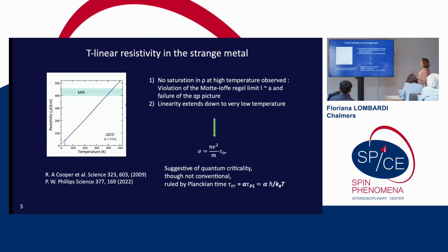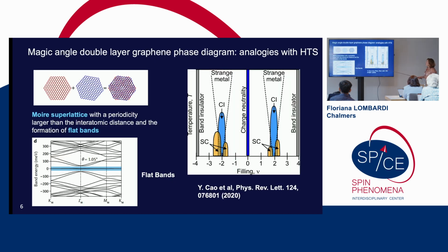is breaking down. But if one takes the usual Drude formula and one takes the transport time, what has been proposed is that if the transport time just depends on temperature and on natural constants, h by kB, then one can retrieve this linearity of the resistivity, and one has started to talk about Planckian time, and that all this physics is related to strong entanglement between electrons.